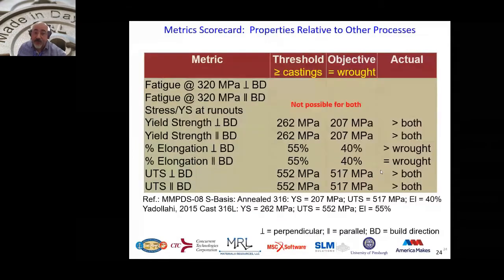So the first thing, for example, what you're looking at on that slide here: the fatigue testing. We intentionally did fatigue testing at 320 megapascal, which was a lot higher than the yield strength of the material, both cast and wrought. So you can see from literature, and we wrote the literature information and the MMPDS S-basis information for the same material. And you can see we fatigue tested the material at even above the wrought properties that you are able to see on the screen.